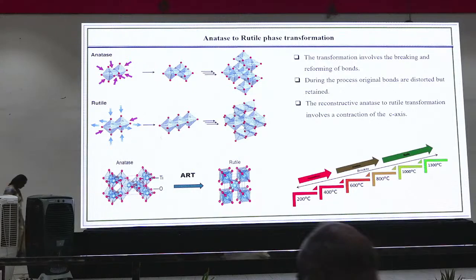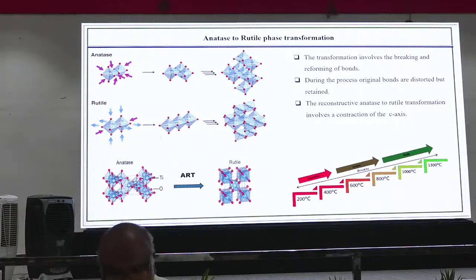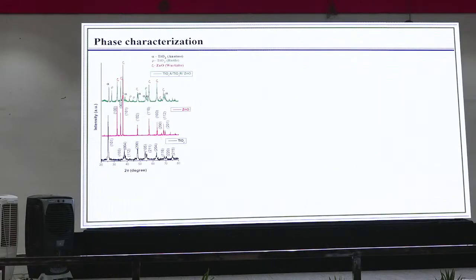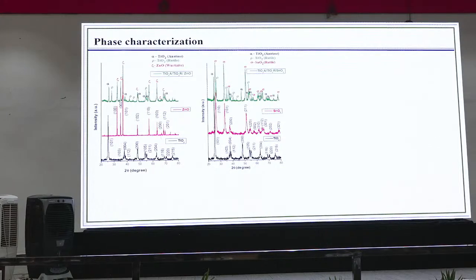Why does it have to happen? Because as the temperature increases, their phases will change. So when I did the ball milling, it produces an enormous amount of heat that converts the anatase phase into the rutile phase. This we have identified using phase characterization by powder X-ray diffraction studies. From the powder X-ray diffraction studies, what I have taken is pure TiO2 and pure ZnO. When we have done the ball milling, we have got the ternary complex of it. We have also tried for SnO2, and when we tried SnO2 also, we got the same. So from this we identify that this transition is because of the ball milling process.